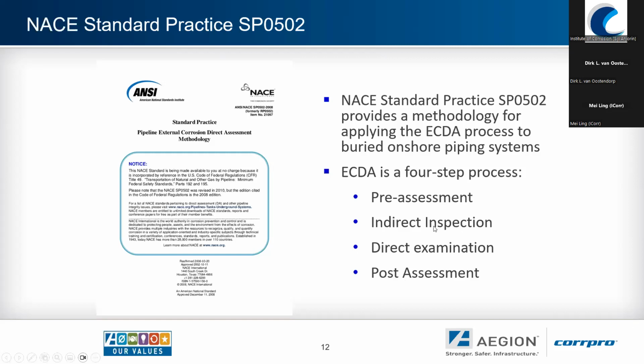From there, it goes into the indirect inspection phase, which is typically your overline surveys along the pipeline to gather the data. The back end of that phase is then the data correlation and risk ranking, which leads to the direct examination phase, prioritized excavations to actually inspect the pipe at pipe depth, conduct some additional in-ditch testing on the pipeline, and then the post-assessment phase is the back end to actually demonstrate that all 4 phases have been completed, demonstrate that the information provided out of the pre-assessment actually did lead to a successful application of the technology. There's a corrosion growth rate calculation portion to the post-assessment, which then also drives the required re-inspection interval for the external corrosion direct assessment application.